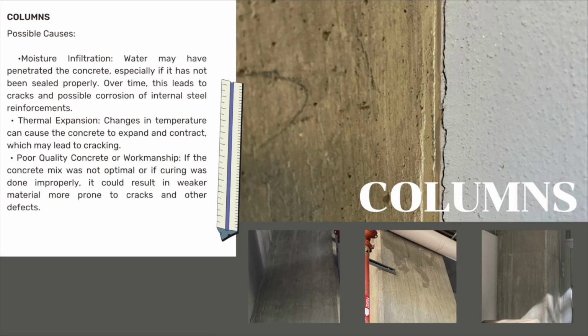Like I said before, some possible causes of these little defects to some of the columns could be moisture infiltration, where water may have penetrated the concrete, especially if it hasn't been sealed properly. Over time, this leads to cracks, and it can even lead to corrosion of the internal steel reinforcement inside of the columns. Another cause could be thermal expansion, which is changes in temperature that cause the concrete to expand and contract, which could lead to cracking. And another reason could simply be poor quality concrete or workmanship.